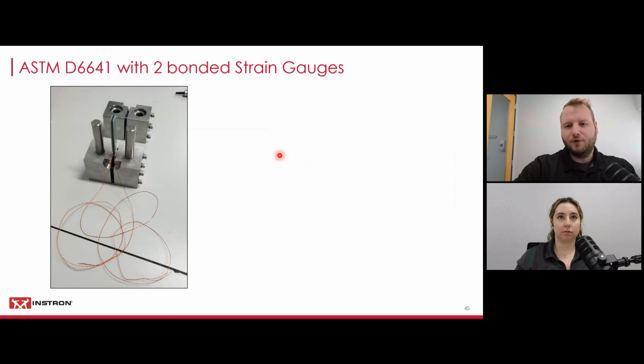This is also going over how you actually load this, because usually people only see the fixtures, but you don't really see how to put a specimen in. So I figured I'll show you that. You need to be really careful now if you're doing this with a strain gauged specimen. It is definitely possible to damage that. I would always recommend for anybody who's not familiar with this process, hasn't done that yet, to just do it with a non-strain gauged specimen first, just to get a feel for it. The fixture is quite heavy. I mean, this is all solid steel.